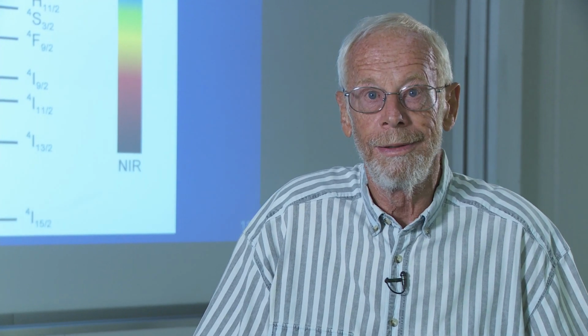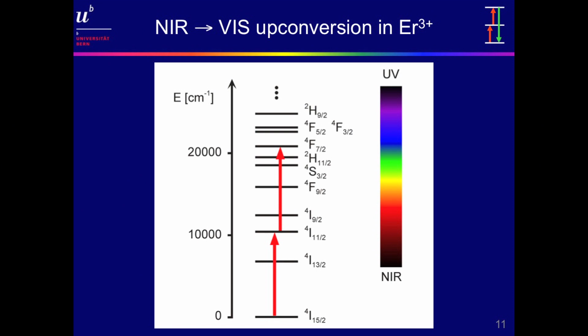Erbium is the upconversion ion par excellence because of its very favorable energy level structure. It can be excited in many different ways by upconversion. Here we see an excitation around 1 micron, bringing it up to quartet F 7/2.